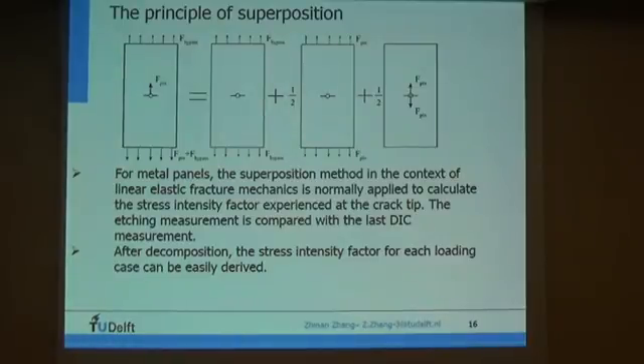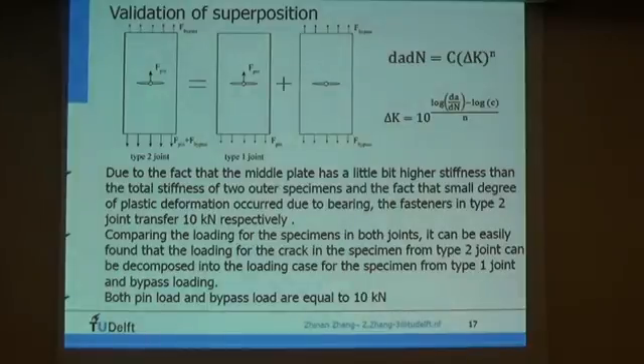So the question is, is it also possible to use the superposition method for the fiber metal laminate joint? So we want to validate this hypothesis. We use the data from the two types of tests, and we also use the Paris equation, and we transform the equation like this. Due to the effect of the middle plate having a slightly higher stiffness, we just talk about the material. The middle plate is the Glare 3 76, so it's the total stiffness of the two outer specimens, and a small degree of plastic deformation occurred during bearing.